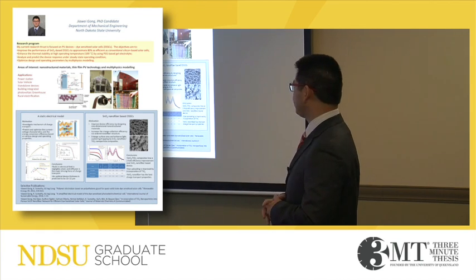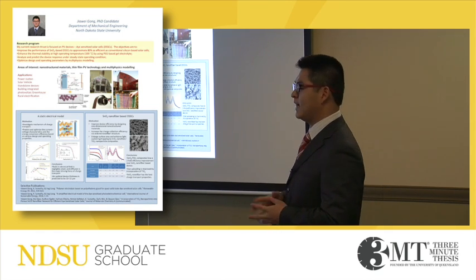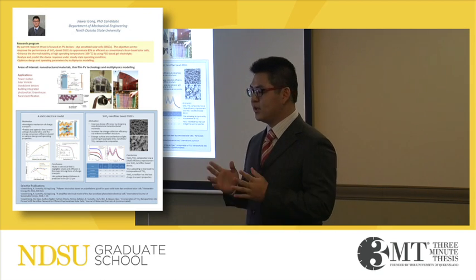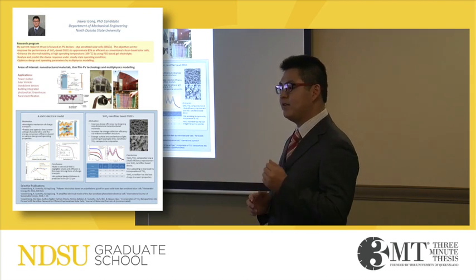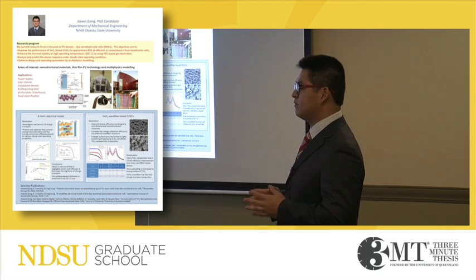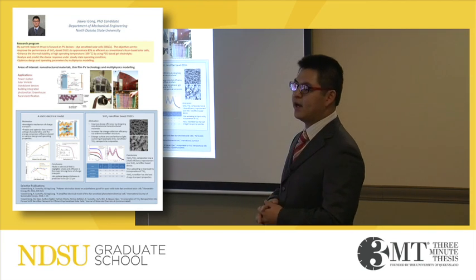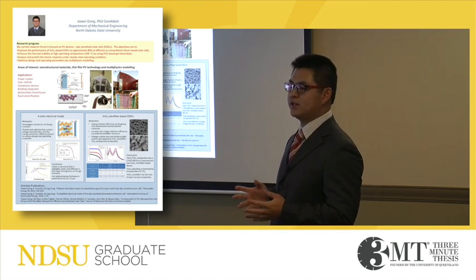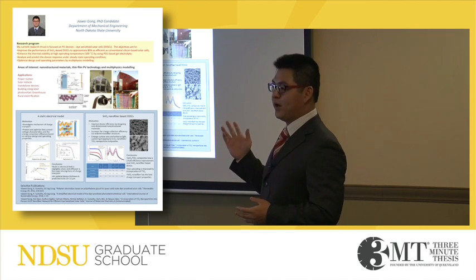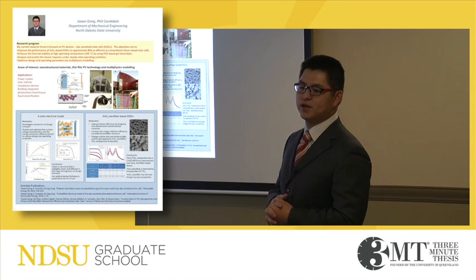This study provided an important guide to future high-efficient dye-sensitized solar cells. Results have shown that the presence of tin oxide nanofibers could significantly increase device efficiency by two-folds, mainly because of effective light scattering and charged transport. These results have been presented in conferences, including one international renewable energy conference in Spain, and the work has been communicated to the Journal of Materials Chemistry A.